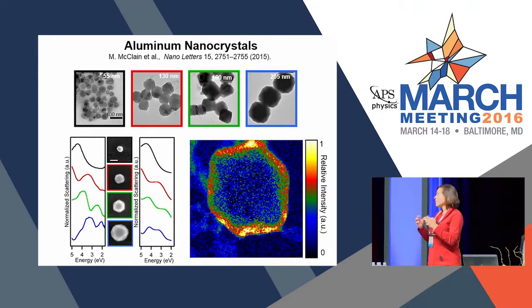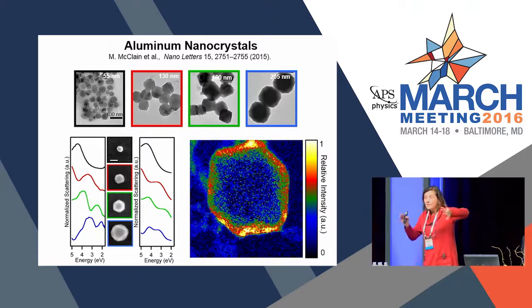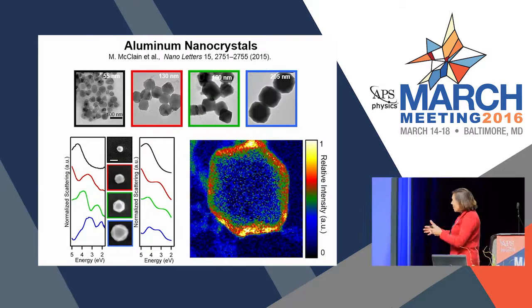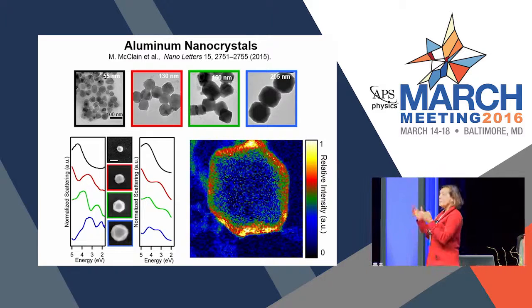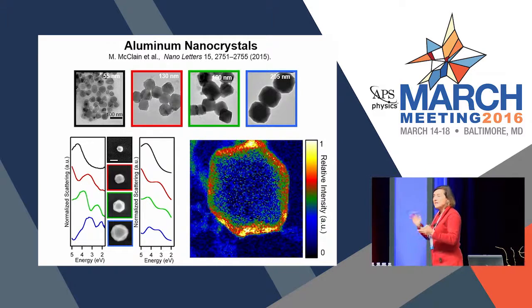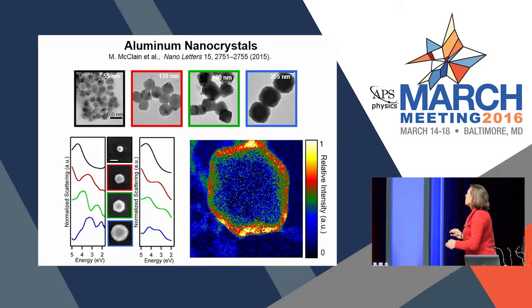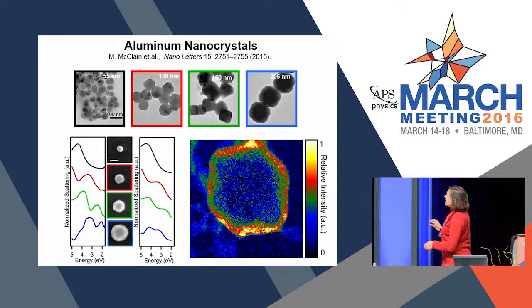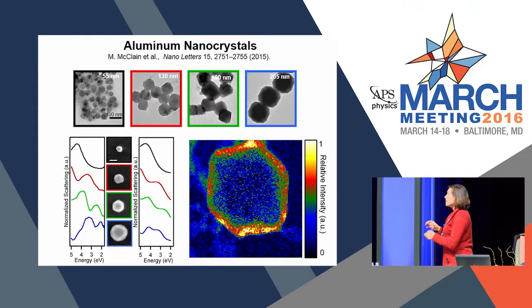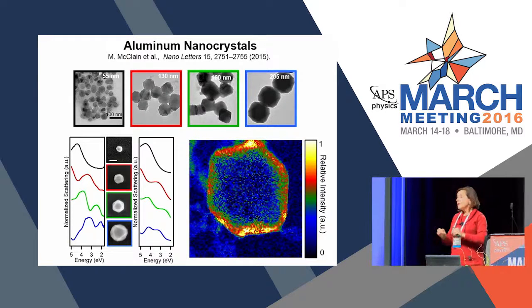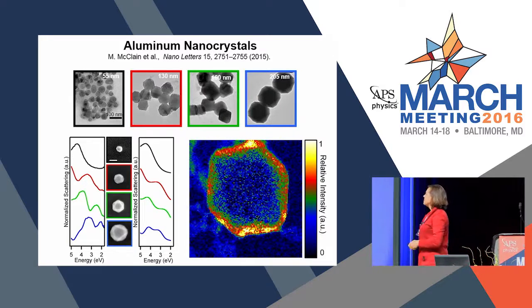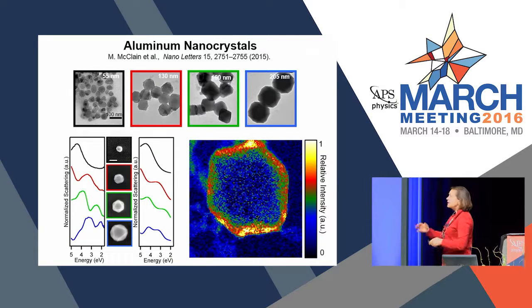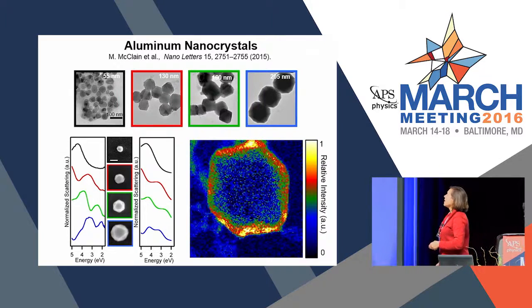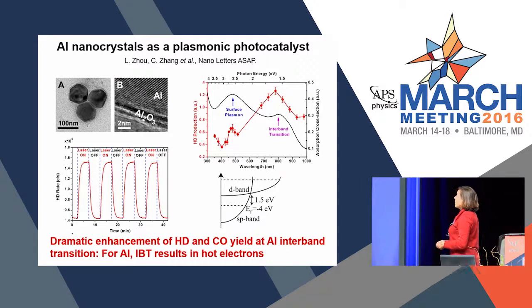But when a nanocrystal grows, it's one of the purest forms of matter that we can obtain, because as it grows, it forces the impurities to the outside and a quite perfect crystal forms. And so the optical properties indicate to us that the aluminum is extraordinarily pure. And if we look at the elemental map of an individual nanocrystal, we see that alumina layer that I mentioned before. It has this between 2 and 4 nanometer capping layer that is robust with respect to further oxidation. And so we do the same experiment.